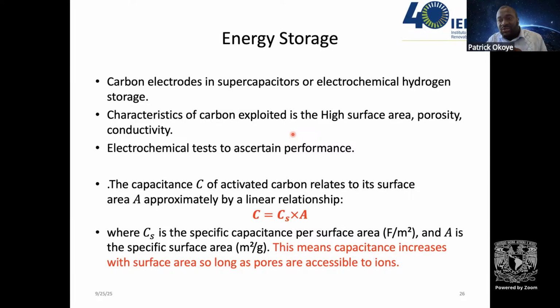And to know the relationship between the capacitance for supercapacitors, or even storage for hydrogen storage, and the surface area, we have this model where CS is the specific capacitance per unit surface area, C is the specific capacitance, and A is the specific surface area. This means that indeed the capacitance will increase proportionally with the surface area as long as the pores are accessible to the ions. Okay?